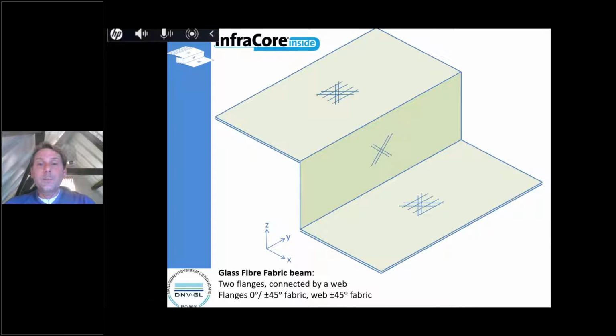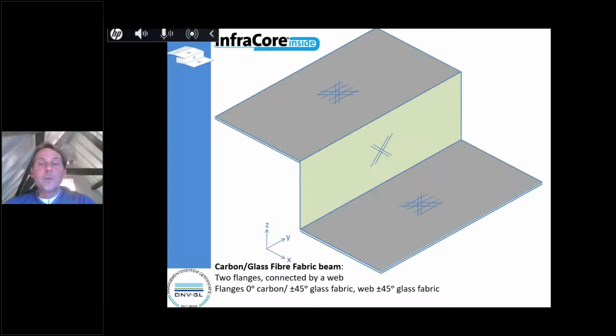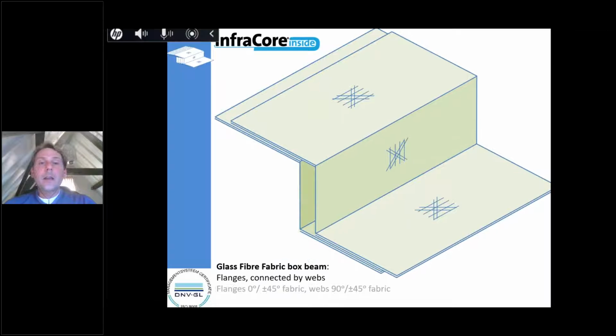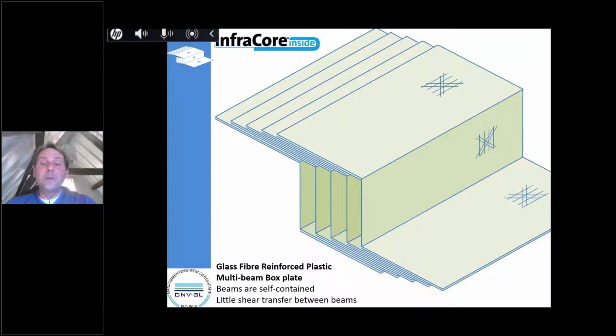So we start with this basic Z layer. We add additional material where deemed necessary, and we just continue stacking those fabric beams. For me, it's very important that you understand that these fabric beams in this phase are not consolidated. These are dry fabrics that are placed into a mold in a very fast and efficient way before being frozen in their end geometry by injecting resin.